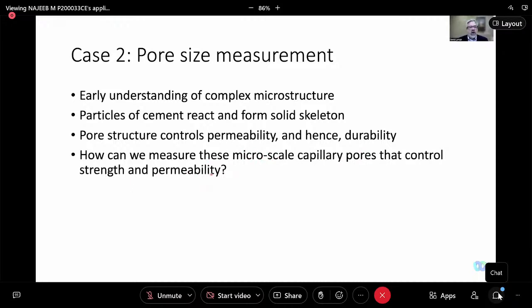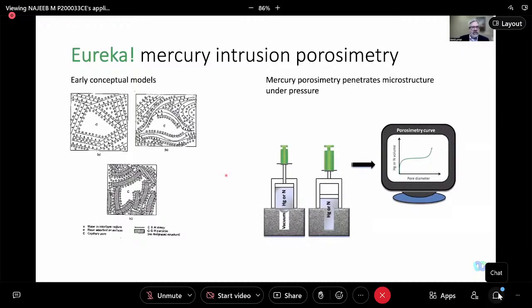There was a very early technique called mercury intrusion porosimetry that was applied to cement research. And I used this back in my PhD, actually. And these diagrams are just here to illustrate the idea of what is the capillary pore between the layers of hydration product. And what we're going to see in this technique is that we take a sample and we pull a vacuum on a volume here, and then we apply high pressure, increasing pressure for the mercury to intrude into our sample. At the end of that experiment, we get a curve that shows you how the pressure is applied, how much volume of mercury went in, and then interprets this as a diameter of the pores that were intruded.